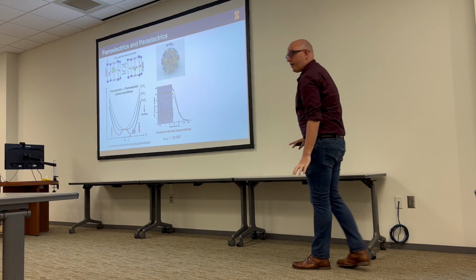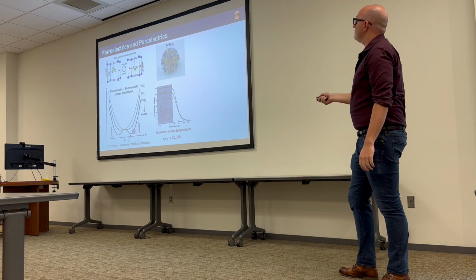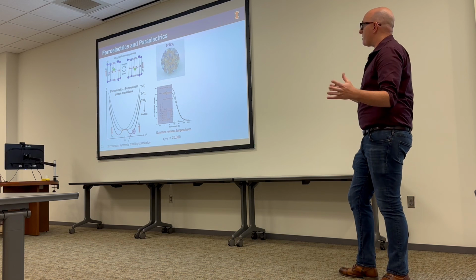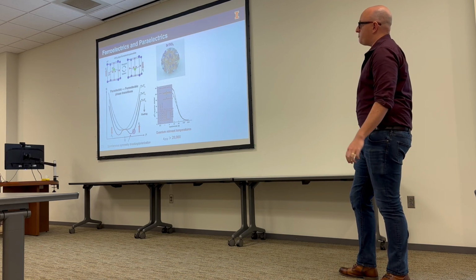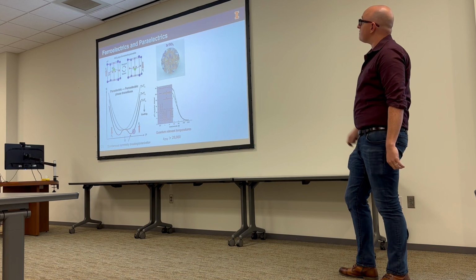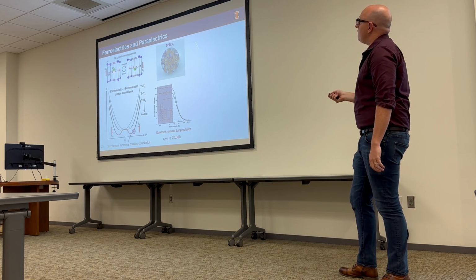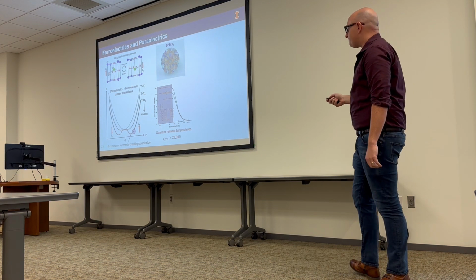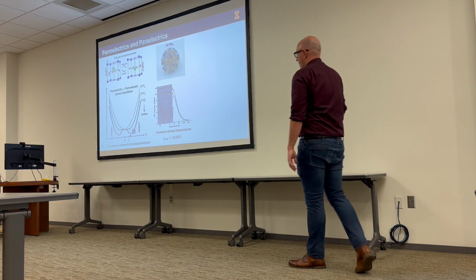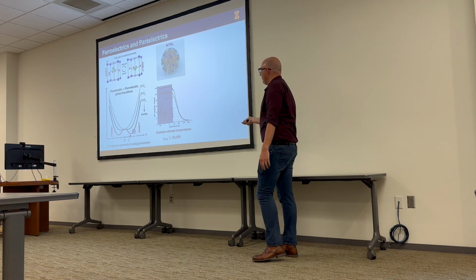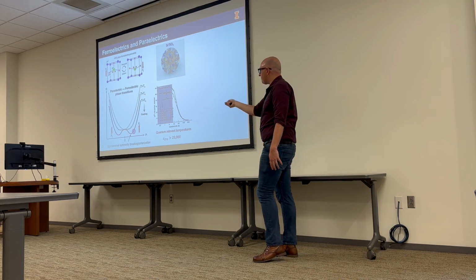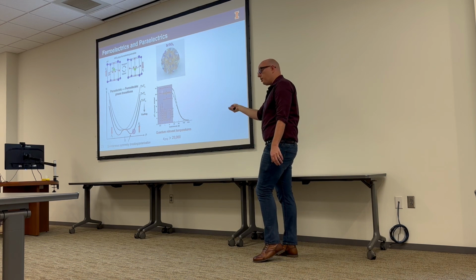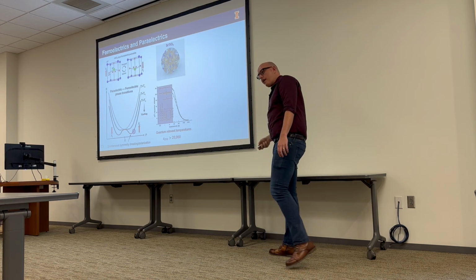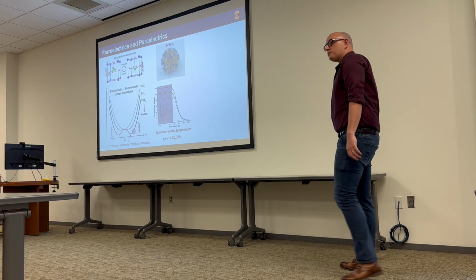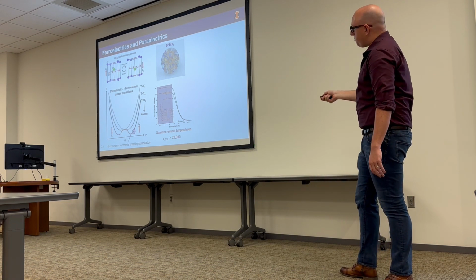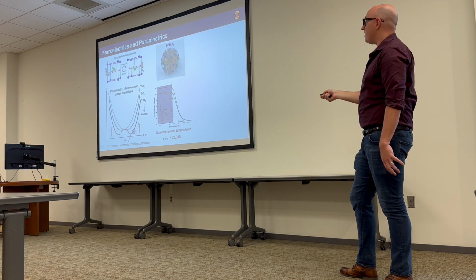The fun part is we found this material. It's strontium titanate, so for condensed matter people, this is an old friend. For people who like fake diamonds, it's also a fake diamond. It's one of these ferroelectric perovskites. And what's great about strontium titanate is, first of all, it's been studied for like 50 years. And if you cool the system down to low temperature, its dielectric constant explodes and goes to over 20,000 in basically all quantum relevant temperatures. And importantly here, it goes high and then stays high.